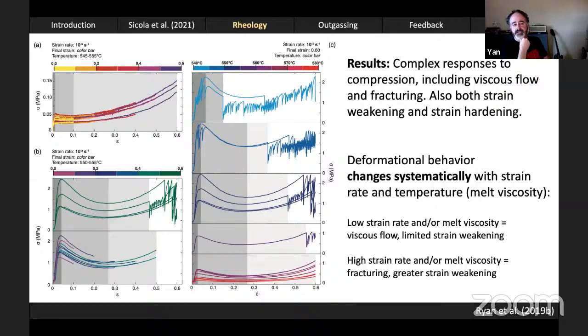So it's quite high. Yeah, in that case, so this is sort of more drawing on what I'm working on now. I'm working on suspensions that are 40%, 60%, and 80% crystals, and there's no bubbles present. But I'm definitely running into the condition when you get up to 60% that really any mechanical response is about the interaction of crystal and crystal. So it doesn't really matter if it's melt, or I would posit doesn't matter so much whether it's melt in between them or vesicles, because you're really just seeing the effect of the crystals, and it doesn't matter what's in the intergranular space. But that's just sort of a rough rheological division, and perhaps depending on the crystal shape and size, there could be a significant effect.